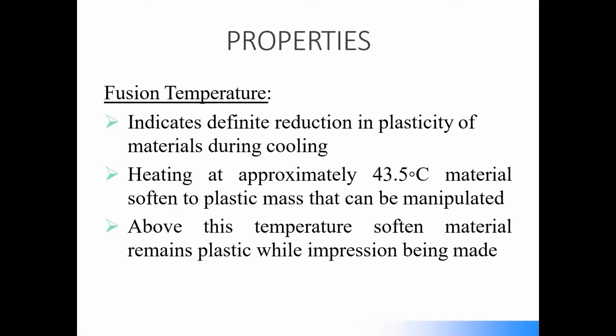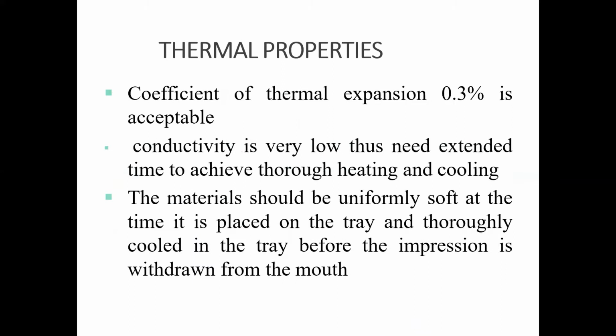Now coming on to fusion temperature, it indicates definite reduction in plasticity during cooling. So heating at approximately 43.5 degrees Celsius allows the material to soften to a plastic mass which can be manipulated. Above this temperature, softened material remains plastic while impression is being made. Coming on to thermal properties, the coefficient of thermal expansion is around 0.3%, which is acceptable.